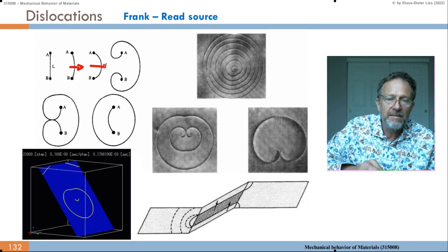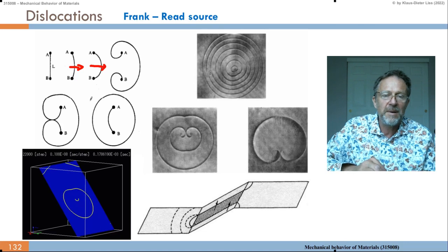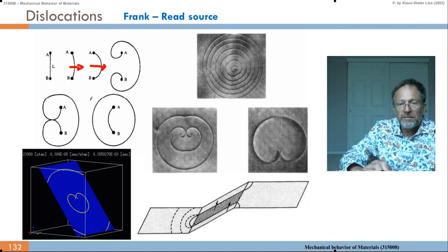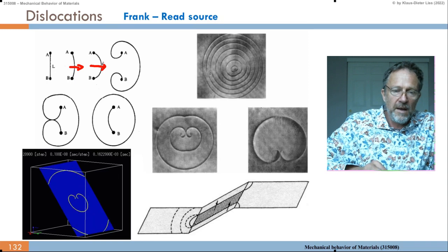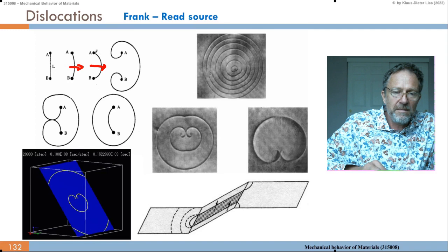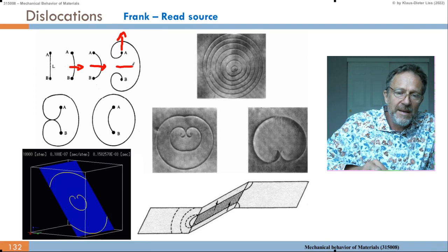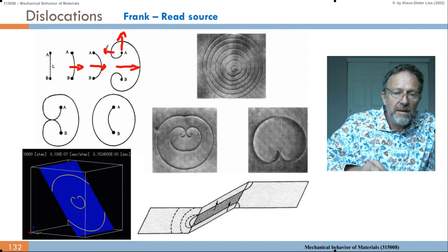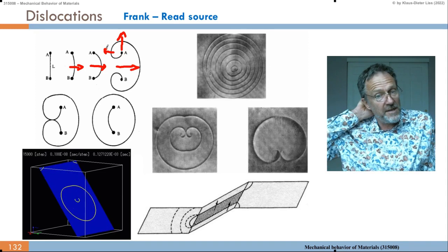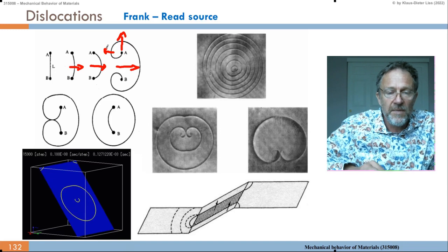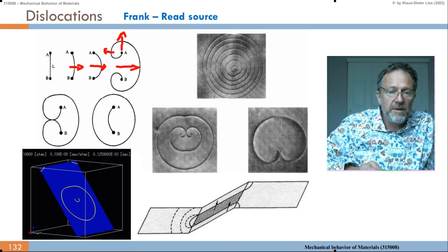Upon further plastic deformation, it bends further, and then we know the edge character becomes a screw character when it bends to 90 degrees, which then moves in the other direction, perpendicular to the shear force, and eventually it expands in the backward shear direction, as discussed in the section about a full dislocation loop.